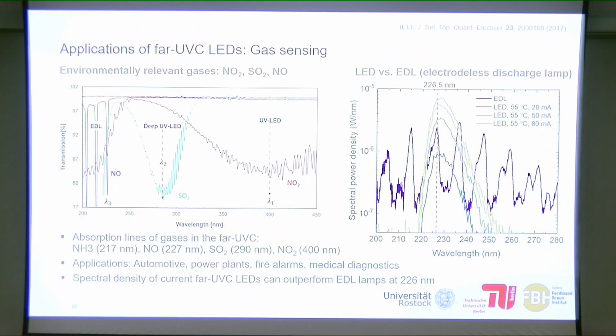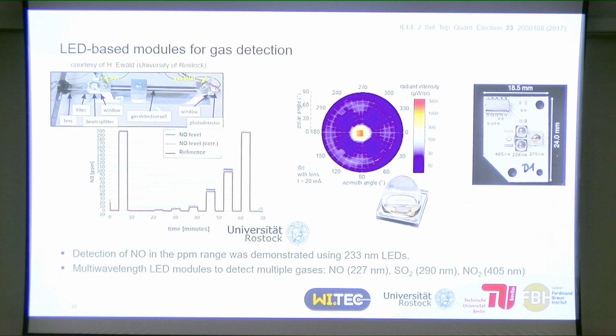Another application is gas sensing. In the far-UVC region, there are many interesting wavelengths for gases such as ammonia, sulfur dioxide and nitrogen oxide. Currently they use electrodeless discharge lamps, but as you can see here, the 226.5 nanometer LEDs that we have already have an intensity which is good enough to use in such sensing applications. We have worked with partners to prove that using far-UVC LEDs we can detect nitrogen oxide in the ppm range, and we're also working with partners to make multiple wavelength LED modules, at 226, 275 and 405 nanometers. The next step would then be to put this all into a package together.